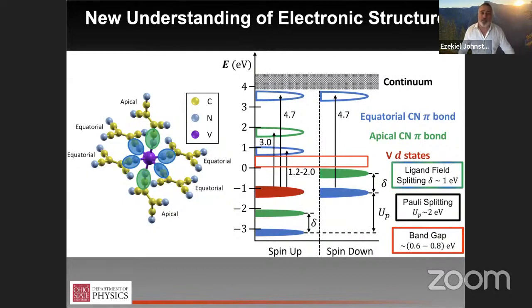That is, I think, more time and detail than typically happens in synthetic chemistry, because they demonstrate the compound, get an initial read of its materials properties, and then move on to trying to synthesize another compound, which is great, and also a very useful contribution to science. But at the interface between the two fields, we would not have had anything to optimize if the chemists hadn't discovered this material. But maybe somewhat immodestly, if there hadn't been a more solid state materials perspective brought to the system, it may not really have been optimized up to the level of the very narrow single peaked resonance for the FMR that we're seeing now.